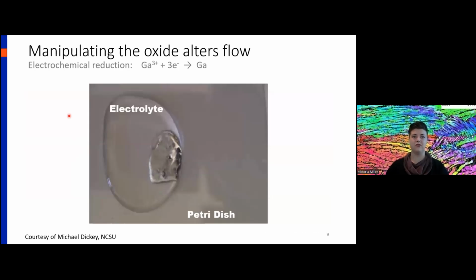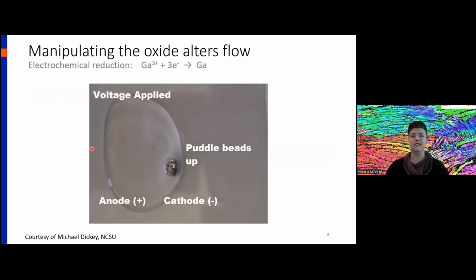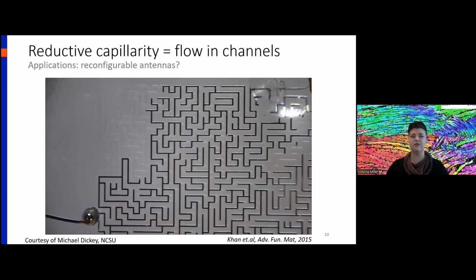This is really interesting, and you can do all sorts of neat tricks, like you can use electrochemistry to manipulate the oxide and alter the flow of the liquid metal. So when you apply a voltage, you increase the thickness of the oxide, causing your puddle of liquid metal to bead up. Inside a PDMS channel, this can be used to create flow into or out of particular channels. So in this case, they're applying a voltage, and just the same way that the liquid metal, the eutectic gallium indium, wanted to bead up before, you can see it is trying to bead up by flowing backward through these channels.